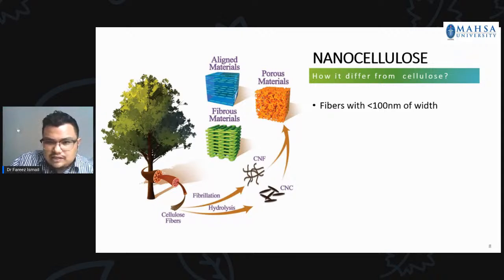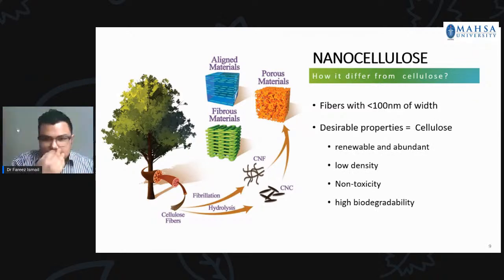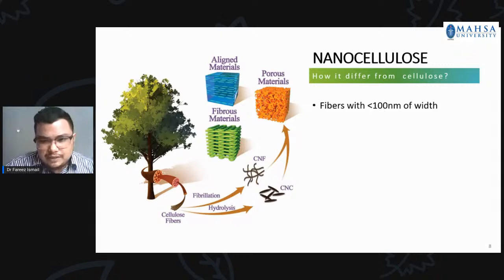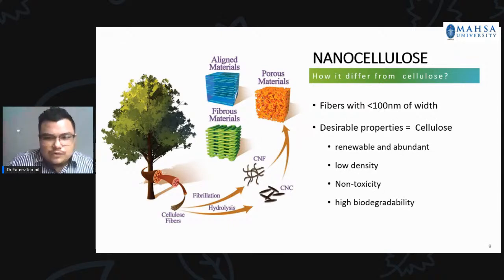And as you can see here, any nanoscale material must have a size of less than 100 nanometers, and therefore nanocellulose, when compared to cellulose, is based on the nanoscale, which is less than 100 nanometers. When you look at different forms of nanocellulose, they are between 2 to 100 nanometers in width, depending on the form. And nanocellulose, which is either isolated from plant waste products or biochemically produced in a lab, holds many of the desirable properties similar to cellulose.